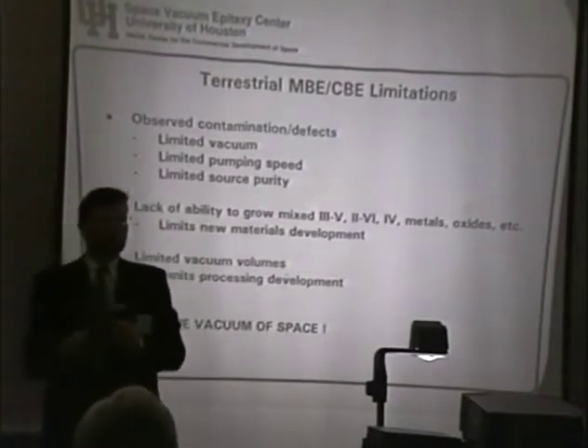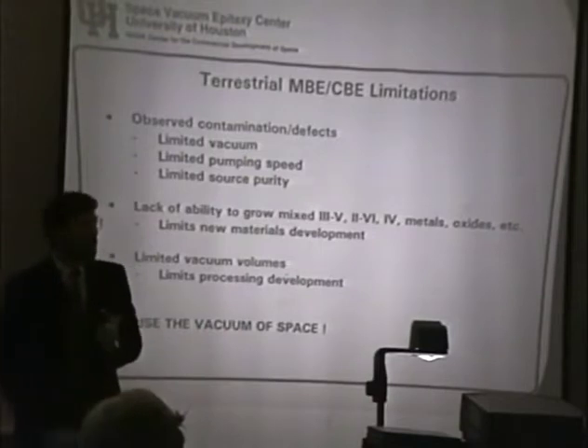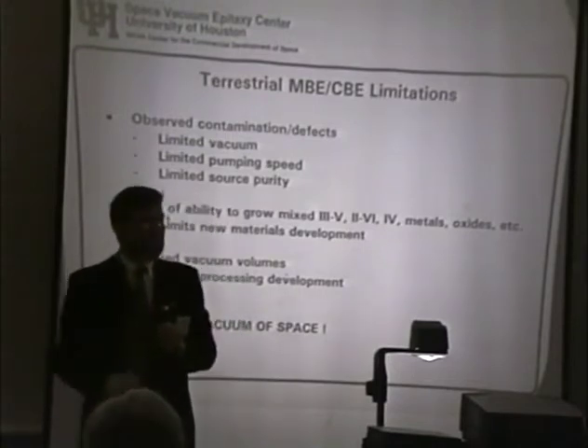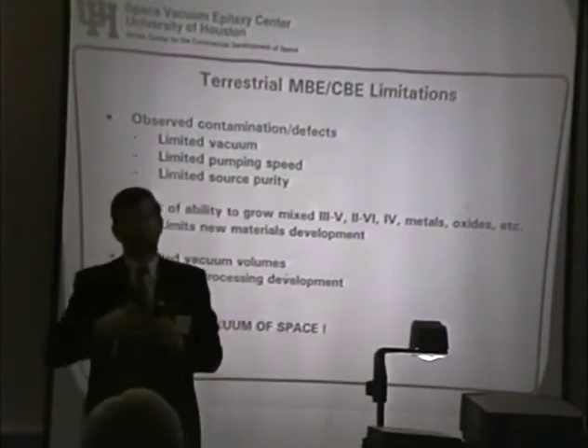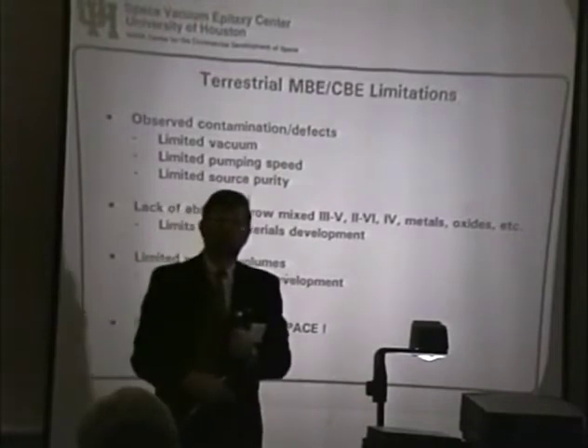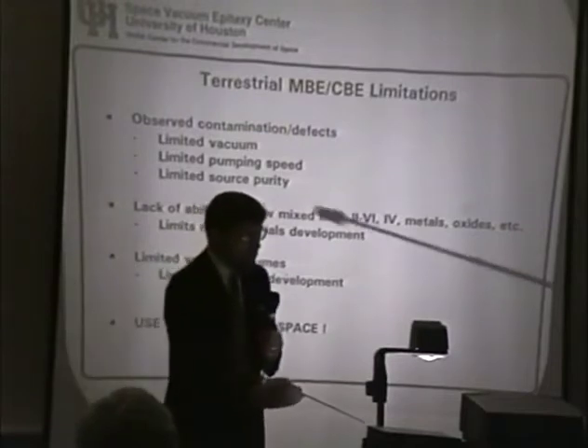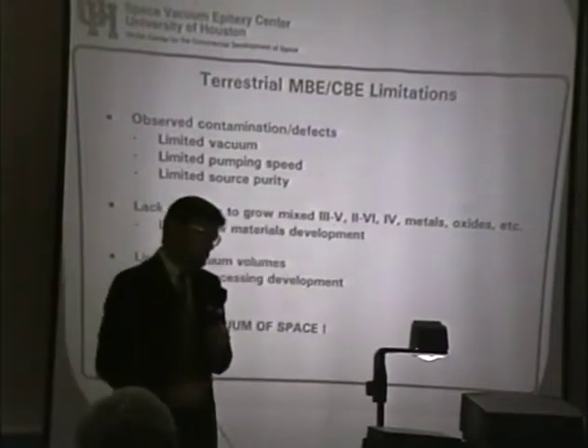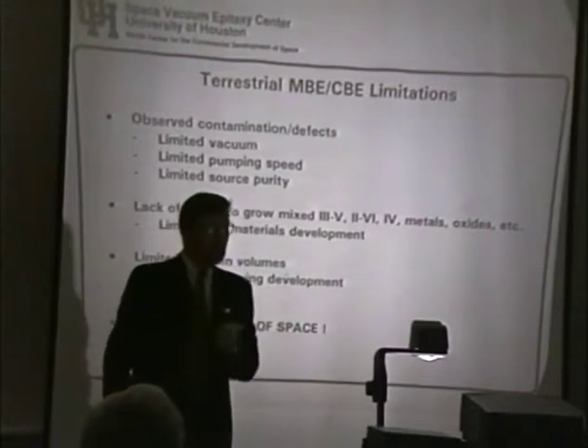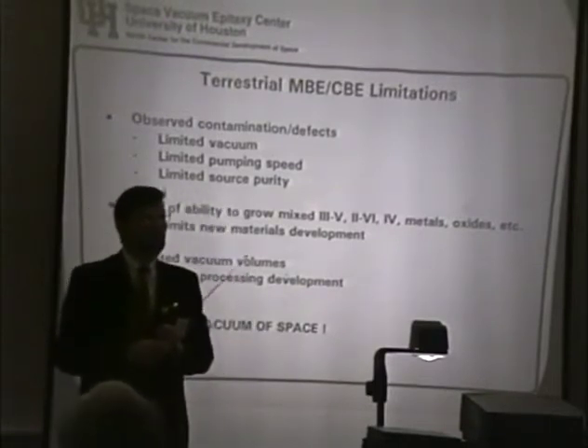We also have the lack of ability to grow a mixture of materials, the alchemistic approach that has been so productive in material science over the past 200 years. Add A to the pot, mix it, add B to the pot, mix it, add C to the pot, mix it. Simply doesn't work here. It turns out that the vacuum chamber you use to make these thin films has walls, and those walls are contaminated by the material you just made the hour before or the minutes before, and that comes off the walls to contaminate the future materials that you make. And so you've got the problem here of not having that wonderful serendipitous effect of making new materials and therefore new performance standards. And you also have very limited vacuum volumes. The best vacuum chambers on Earth, the highest quality vacuum chambers, have the size of the order of this view graph projector in the stand.